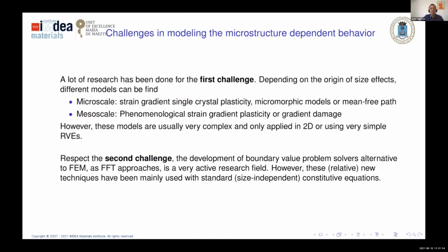So these challenges have been, of course, studied in the literature. For the first one, there are a lot of models that introduce size dependency. In the case of the microscale, we have strain gradients in crystal plasticity, micromorphic models, and others. In the case of the mesoscale, we have other similar approaches, but normally these models are very complex and are applied under simplistic approaches, so it's difficult to find these complex models applied in complex three-dimensional simulations.